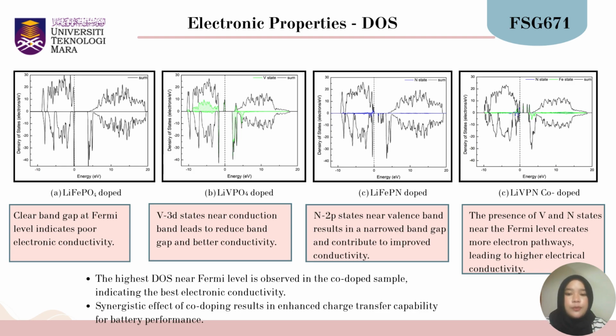With vanadium doping, new V 3d states appear near the conduction band. This helps reduce the band gap and allows the electrons to move more easily, so it improves the conductivity. For the nitrogen doping, we see N 2p states near the valence band, which also narrows the band gap and boosts conductivity. The best result is in the co-doped sample. Both V 3d and N 2p states appear near the Fermi level, creating extra paths for electron movement.